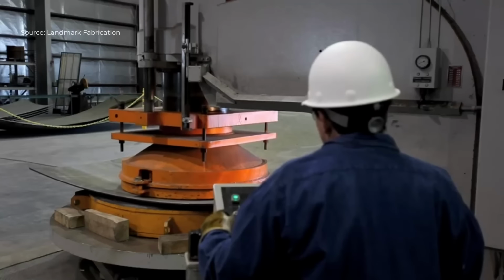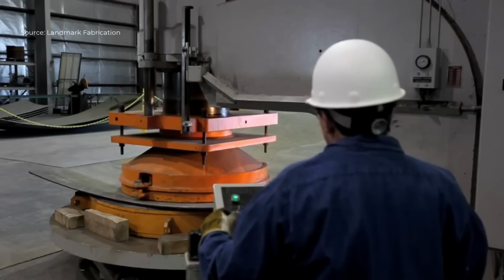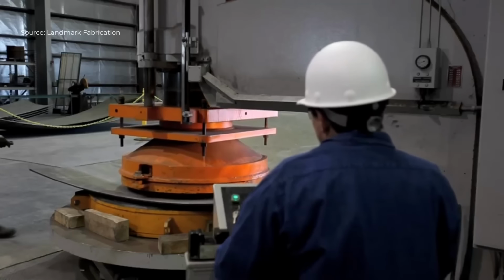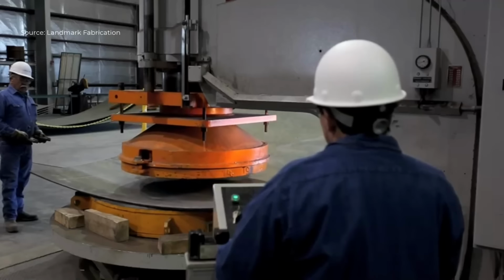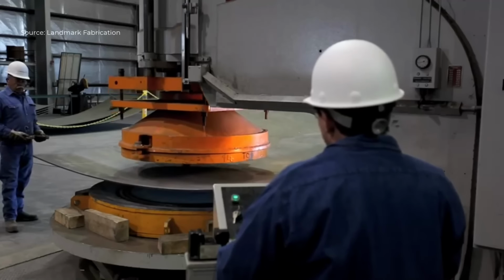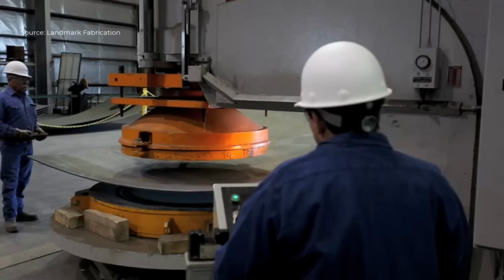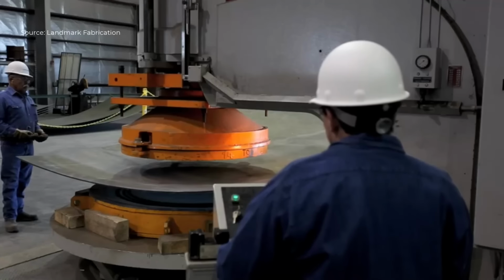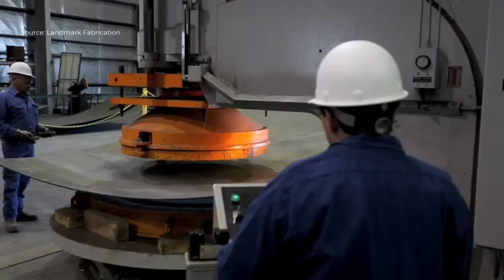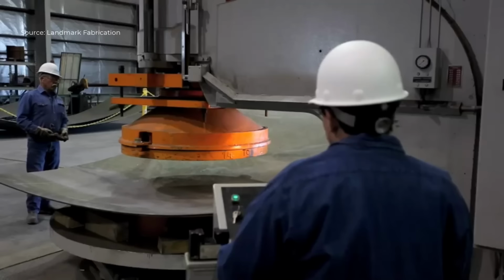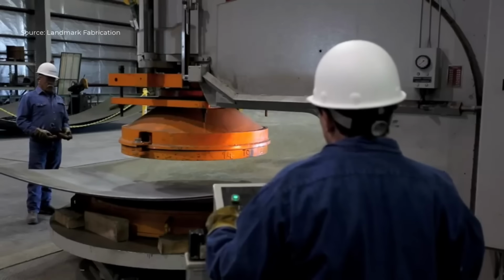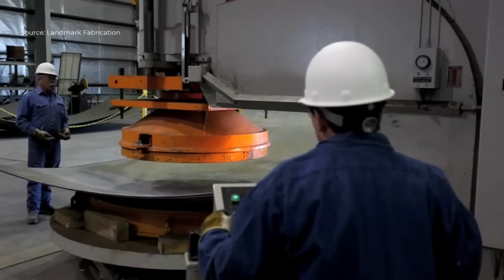Throughout the operation, die alignment and lubrication are critical to ensure smooth metal flow and prevent wrinkles or cracking. After the first pass, the plate may be rotated or re-indexed to achieve uniform curvature. Final inspection verifies that tolerances and surface quality meet ASME U and R stamping requirements.